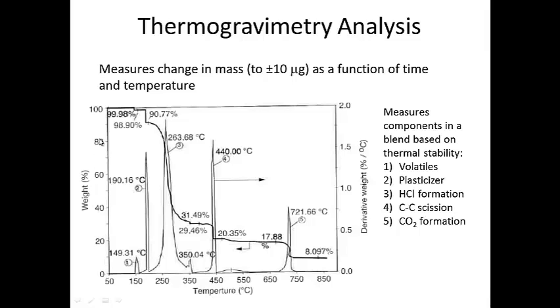If we look at the plot on the left we notice it's measuring the weight percent of the sample. The sample starts out at 100% weight at relatively low temperatures. But then at a temperature of approximately 150 degrees Celsius we see a slight decrease in the mass of the sample. This corresponds to a sudden change in what's called the derivative weight or the percent change in weight per degree Celsius. This little spike down here in the spectrum.